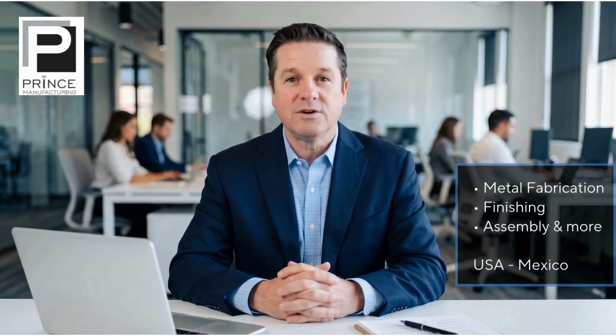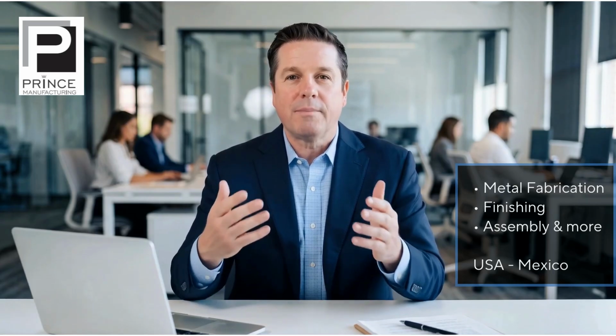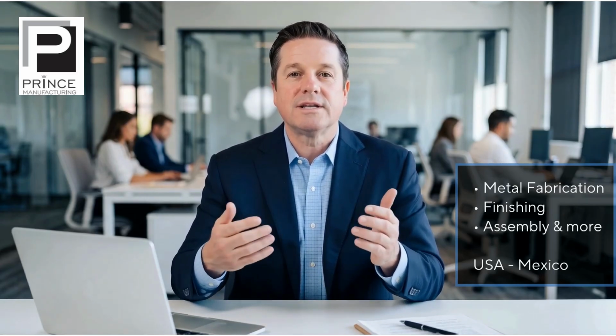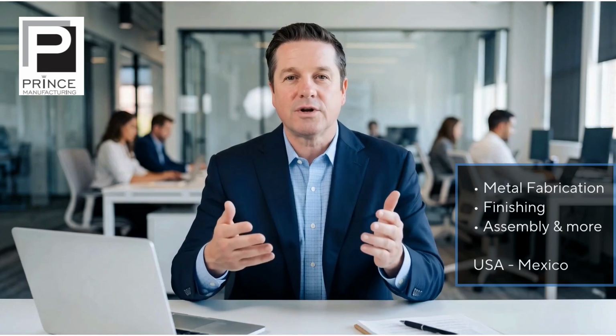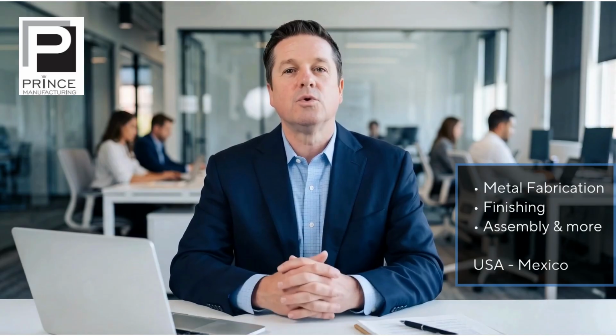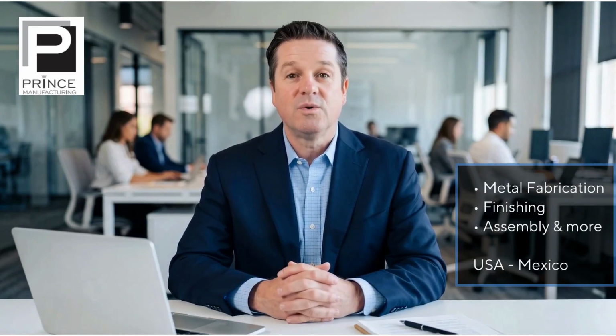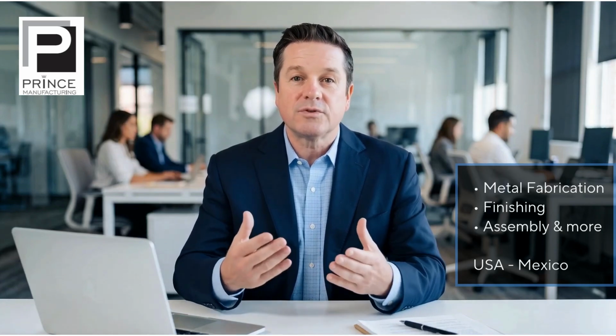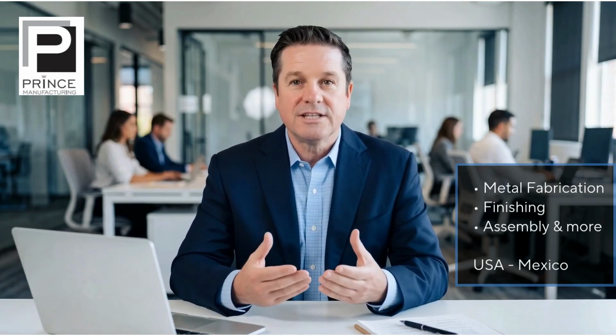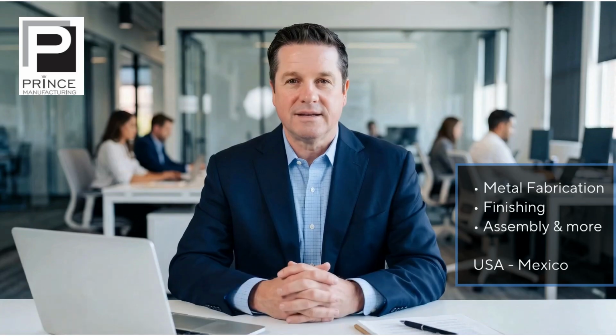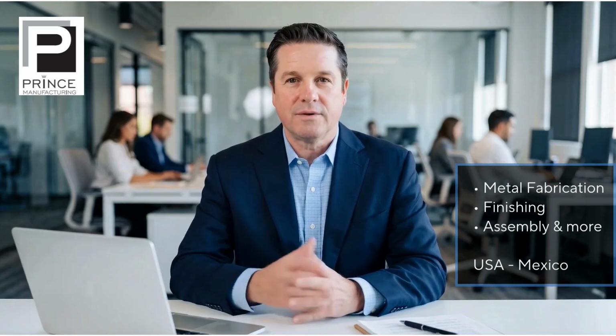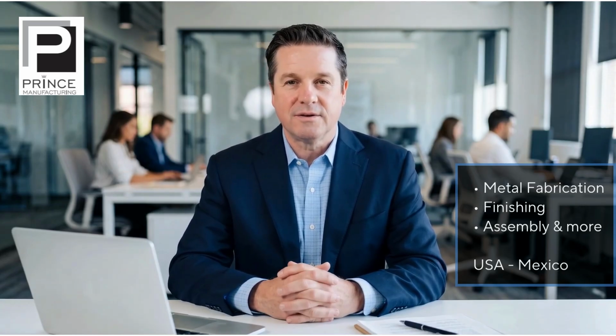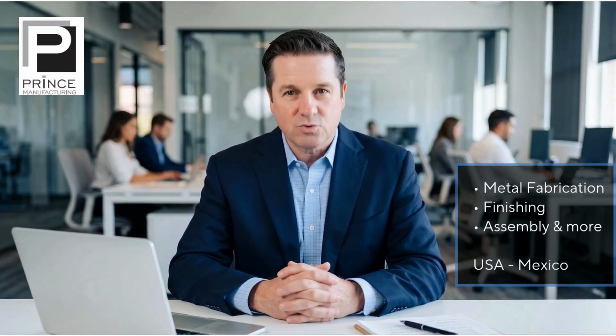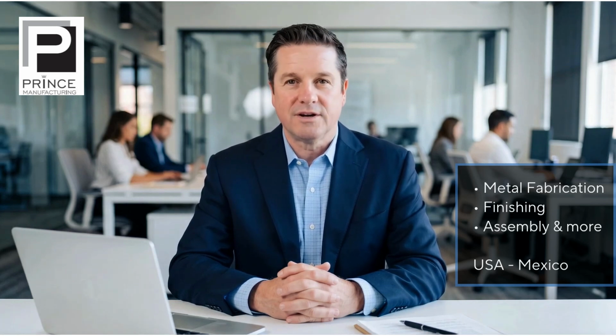Let us look at 3 practical examples. First, an electrical busbar component. A copper or aluminum busbar may need corrosion protection while maintaining electrical conductivity at bolted connections. A heavy insulating coating over the entire component could interfere with its function. The solution may involve selective plating, conversion coating, another specified metallic deposit, or selective masking. The electrical, thermal, corrosion, and assembly requirements need to be considered together. Second, consider an outdoor fabricated electrical enclosure. This part may face moisture, condensation, ultraviolet exposure, corrosion at edges and welds, handling damage, and long-term cosmetic requirements.